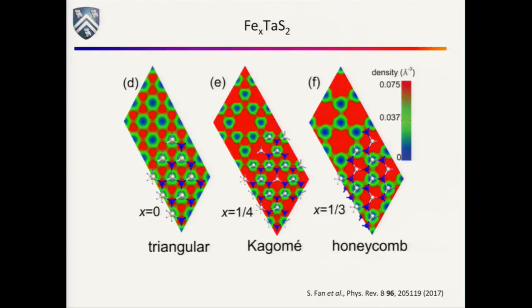This is from a recent paper by Jan Musfeldt's group. This is DFT that they throw in there. If you want to understand how charge is distributed, for the iron a quarter, what you find is that charge in the plane where the irons are is distributed in sort of a Kagome lattice arrangement. In the case of the iron a third, it's more of a honeycomb type arrangement. This iron a quarter is ferromagnetic, and the TC is about 160 Kelvin. This is also ferromagnetic. The TC is more like 90 or a little lower.